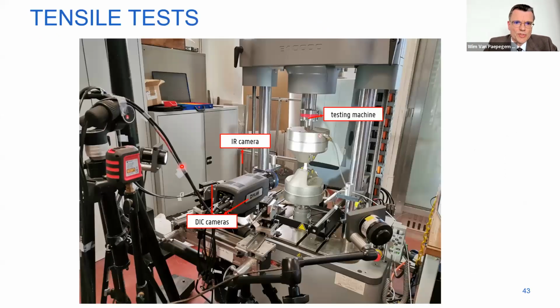Here you see a picture of a typical experiment in our lab. So here you have the sample, which is clamped. And here you see the infrared camera. Remember the temperature measurements I showed you before. And here you see 2 cameras, which are measuring in a contactless way, an optical way, the strain on the surface. This is with digital image correlation.